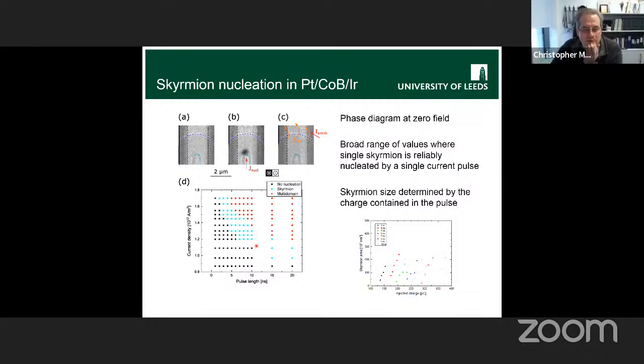And it turns out that we have a bit of control over the size as well. If we calculate the charge contained in the current pulse, then for a given duration of pulse, we get these straight lines of the skyrmion area. So we've got like a balloon that we're inflating up to a certain point, and then the current switches off and it stops.